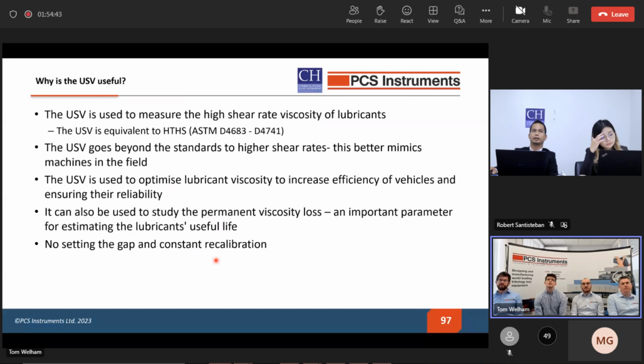Just to summarize then, the USV is an accurate and adaptable high shear rate viscometer. It can be used to measure viscosity under realistic shear rates, meeting many standard conditions, and it can go to higher shear rates than the standards. So this will allow you to optimize the shear thinning effect of your lubricant, as well as being able to characterize the permanent loss of viscosity that a lubricant might experience. So I'll pause now for the translation.